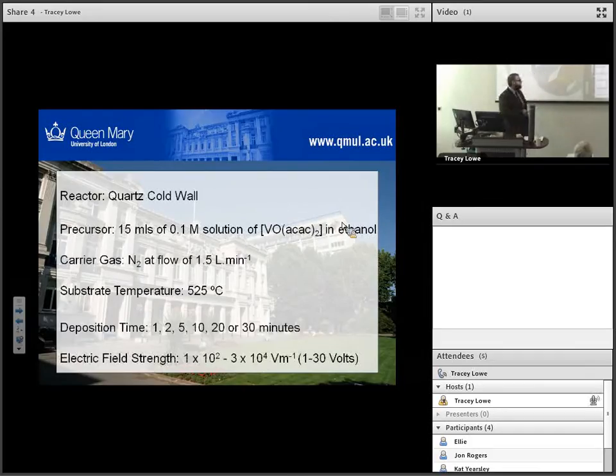We're using a standard solution, 0.1 molar vanadyl ACAC. We're keeping our gas flow rate and substrate temperature the same, and just looking at differences in deposition time and electric field strength. We've previously worked out that these are essentially the best conditions to grow vanadium dioxide films.